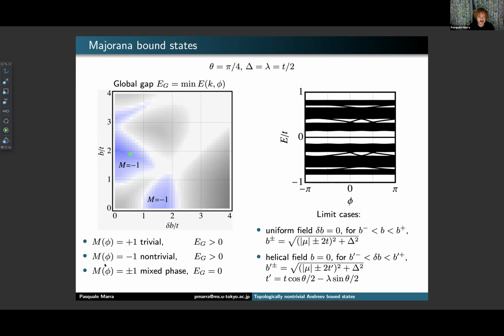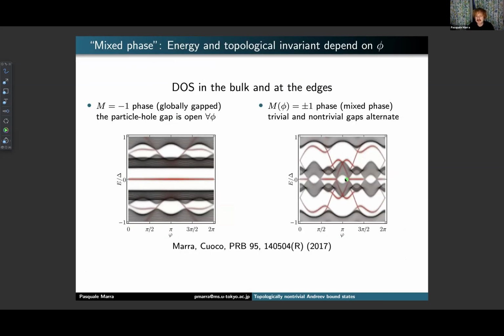So one can have a trivial Majorana number, which are these gray areas with no Majorana bound states. One can have a non-trivial state with a non-trivial Majorana number, and these two patches correspond to the well-studied cases of a uniform field or a purely helical field. And these patches can be seen as a perturbation of these two limits. Then one has this white part here where the global gap is 0. That means that the gap closes for a certain value of the phase phi, and one can have different values of the Majorana number. So we call this a mixed phase. This is the topic of a previous work.